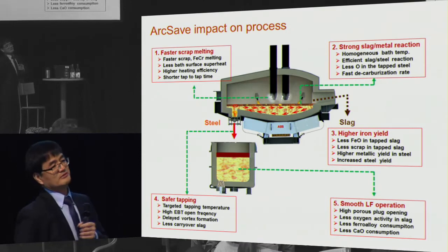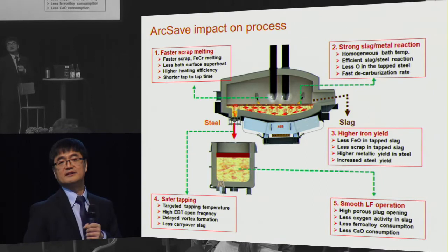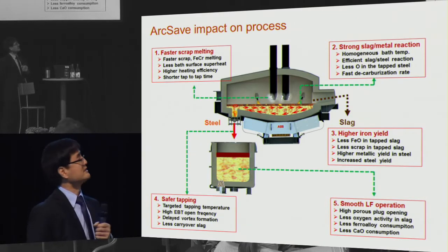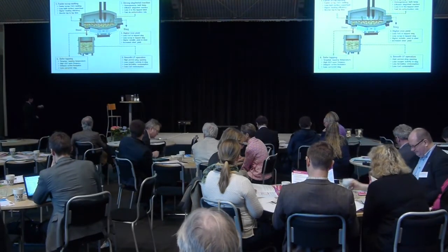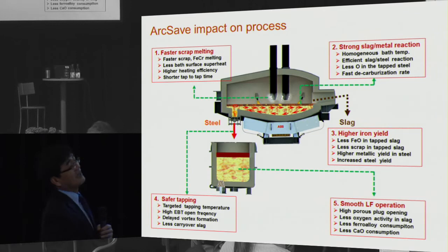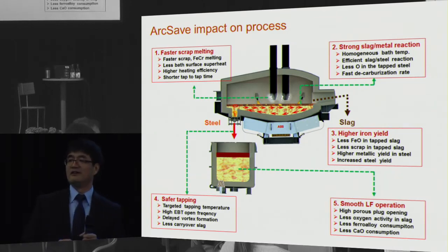From the test, we started the hot test in June last year. We have 6 or 7 months of results. We found that with this stirring, scrap melting is faster, which we also know. The second is that the slag and metal reaction is much faster. The main indication is that the decarbonisation rate is almost doubled. That means if you have high carbon charging at the initial start of the furnace, like hot metal charging or pig iron charging with high carbon, then there is no problem.